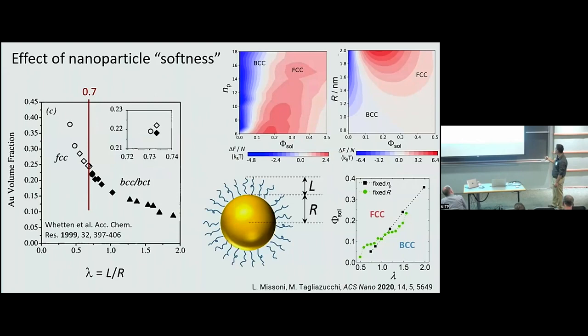And something that is nice about that is if we extrapolate to zero solvent here, we get something like 0.5, which is not that far away from 0.7. So even though, of course, the chemistry here may play a role, and there may be some differences between different inorganic cores, for example, I think there is some generality there, too, in what you get.